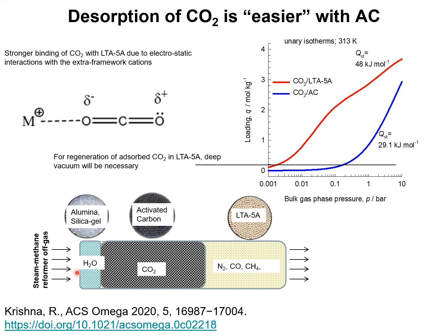In practice, a steam methane reformer off-gas mixture is fed to a bed packed with three different adsorbents. First, alumina silica gel, which has the task of removing any trace water in the feed mixture. Then a layer of activated carbon, whose primary task is to adsorb the CO₂. And this is followed by a layer of 5A zeolite, whose task is to produce hydrogen of the required purity by adsorbing the remaining impurities: nitrogen, carbon monoxide, and methane.